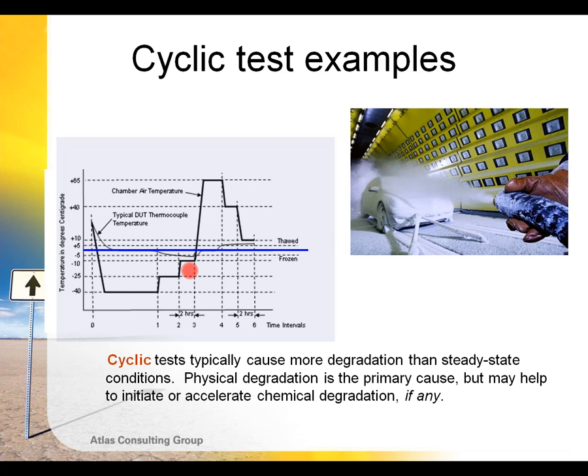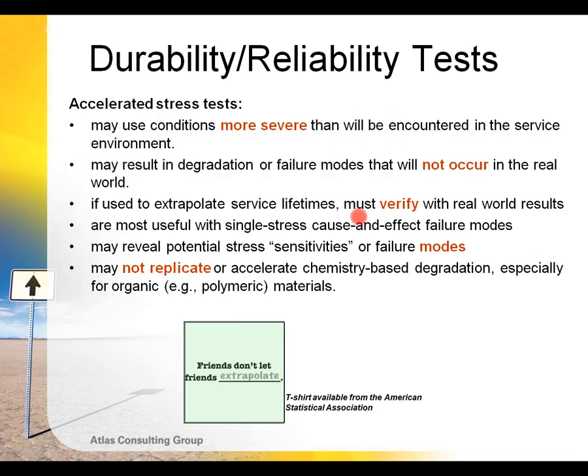We need to understand what is happening to the product sample. So you will see that because the test times here were fairly short, there wasn't sufficient time to allow the product to reach the actual equilibrium temperatures that were really required. So there was nowhere near what the product was actually seeing in this case. So all accelerated stress tests, not just weathering tests, but all accelerated stress tests, may use conditions that are more severe than will be encountered in the field.